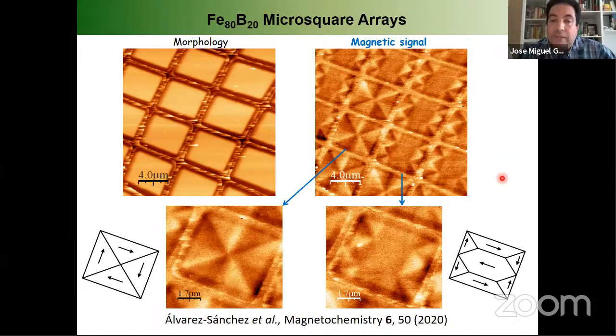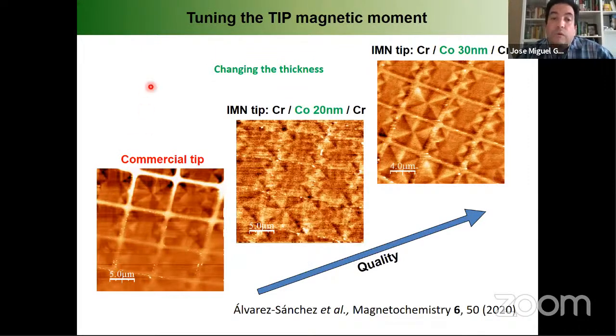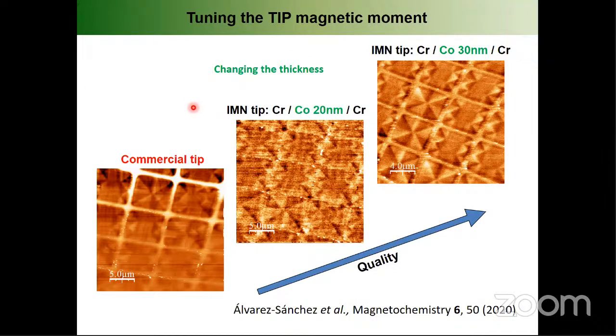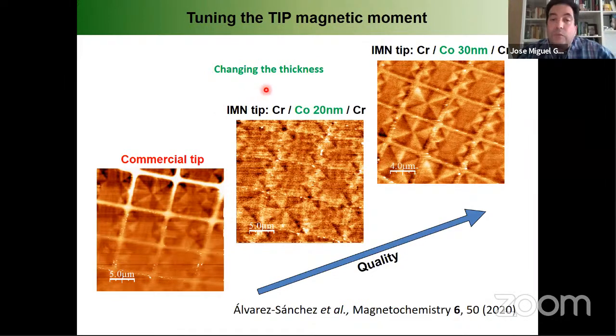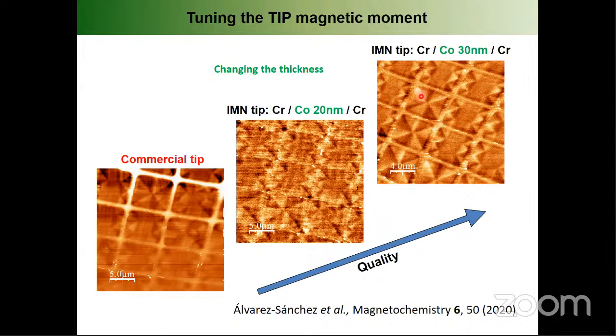But in order to get this nice image, we have to work previously, because using a commercial tip is not a good idea. You can see here, using a commercial tip, you start having some contrast, but the contrast vanishes as the image is taken. So we have to prepare our own tips with a sputtering coating, standard silicon tips with chromium, cobalt, chromium. With 20 nanometers of cobalt, you can see that we start distinguishing the structure, but with a low signal to noise ratio. And finally, with 30 nanometers of cobalt, we obtain this nice image.